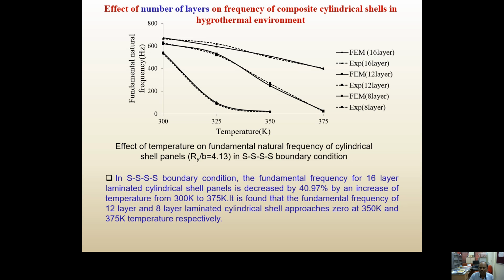So there is an 8-layer specimen, a 12-layer specimen, and a 16-layer specimen. With increase in number of layers, the frequencies increase, and the 8-layer specimen is reaching negligible stiffness at 350 degrees, but the 16-layer specimen is still having sufficient stiffness at 375 degree temperature. This happens due to the effect of bending-stretching coupling.